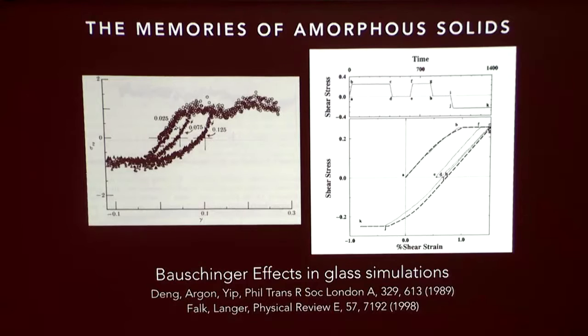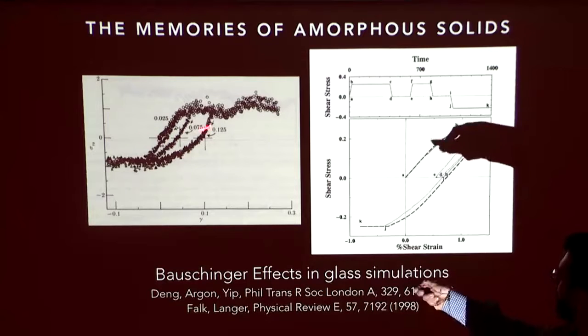It's not that it has a lower modulus in that direction, it's that it has an earlier yield stress or a smaller yield strain also. Are these experiments done by applying the stress and measuring the strain, or by applying the strain and measuring the stress? I'd have to go back and check this one.